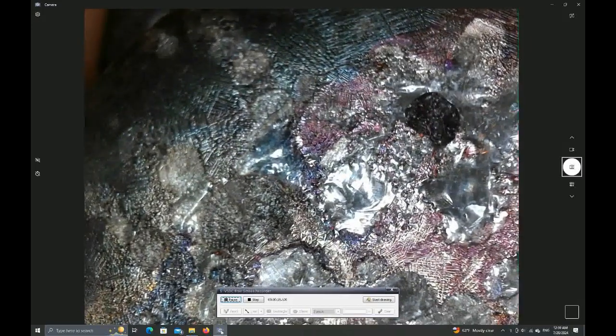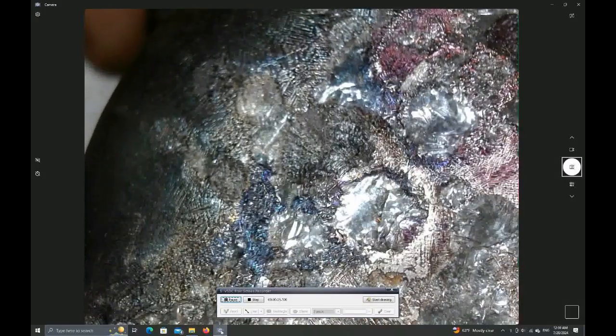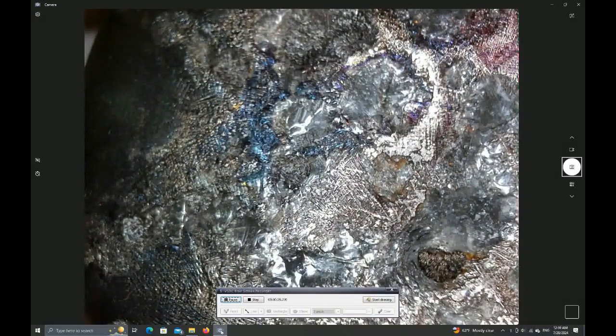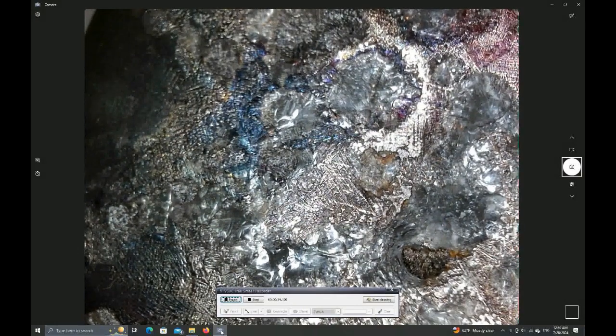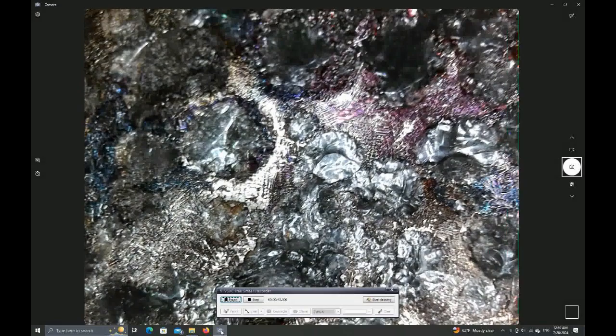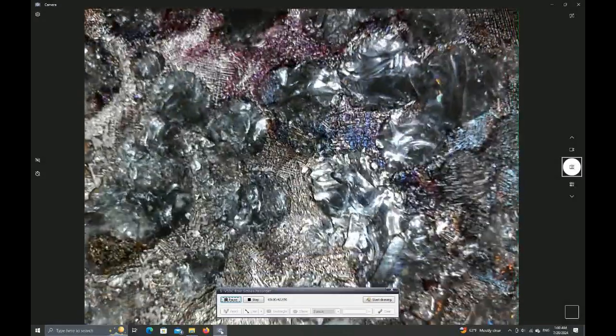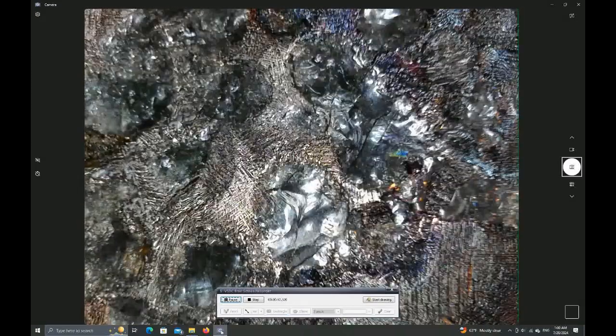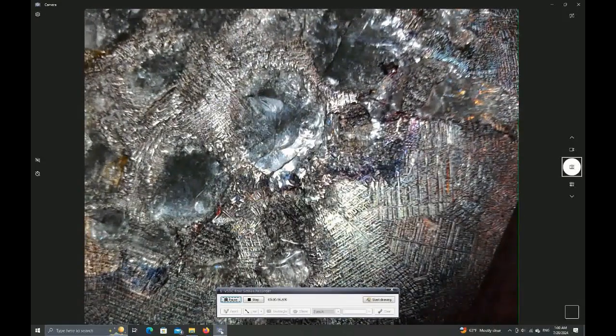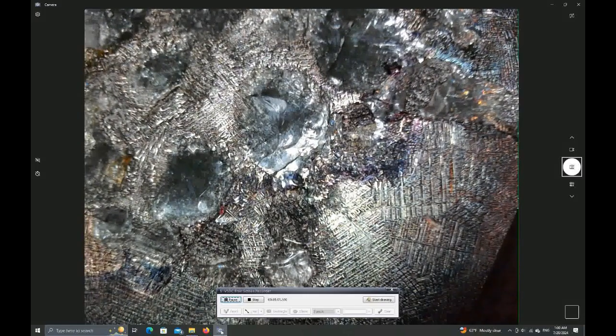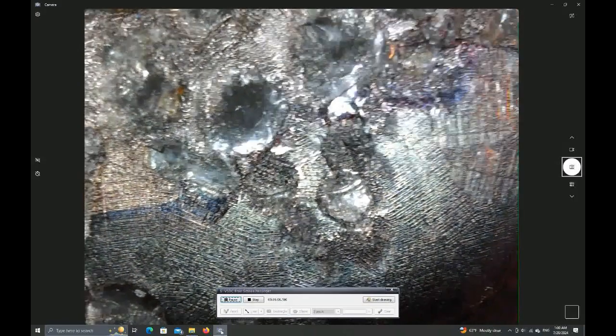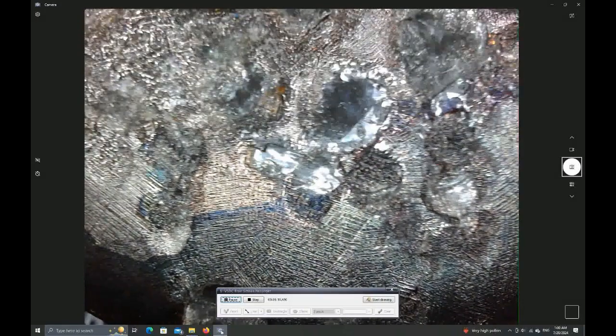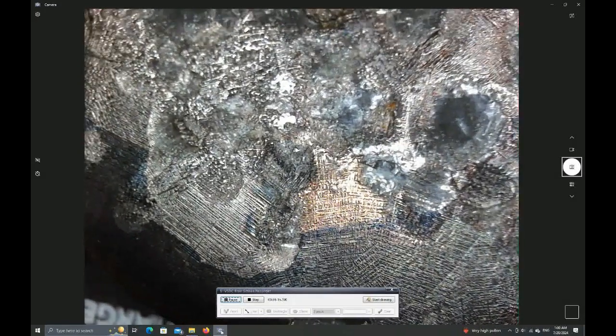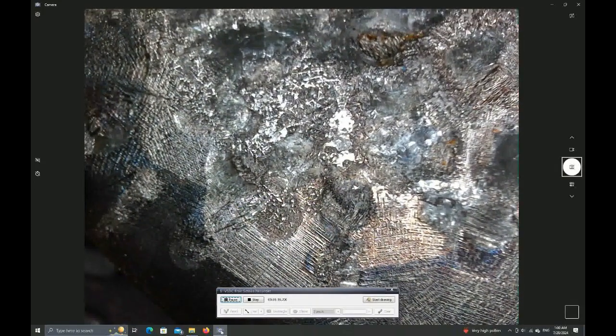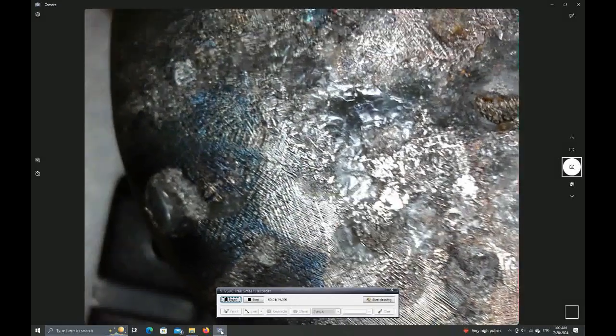But the forced air propane forge lends itself to much better performance, I think, in the production of crucible steel, because you have a much larger thermal mass attributed to the body, the refractory lining of the forced air propane forge, and that itself will help to slow down the cooling rate of the crucible ingot. When you slow down the solidification of something that forms crystals, those crystals get much bigger because they have more time to grow as the phase transitions from liquid to solid. It's the same reason why snowflakes are generally really big when the temperature is right around the freezing point, because at that temperature it takes them a very long time to transition from liquid drops of humidity or whatever in a cloud to solid snowflakes.